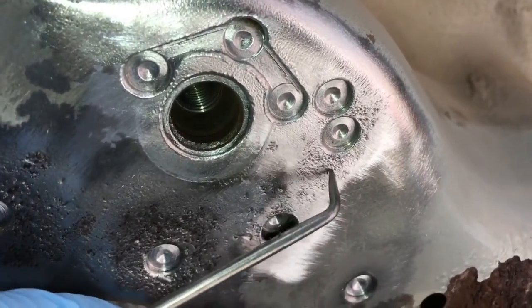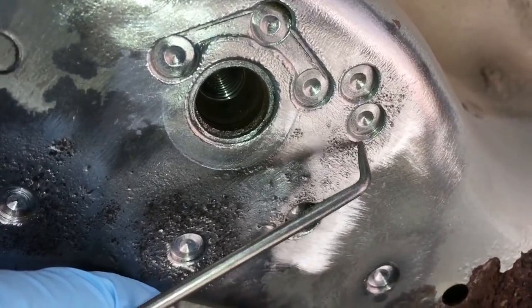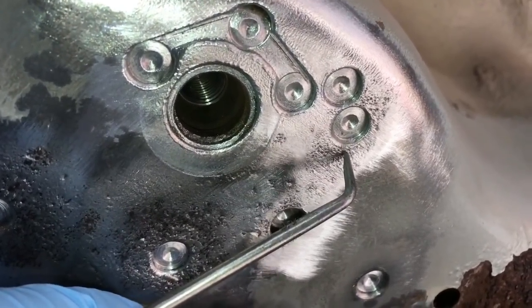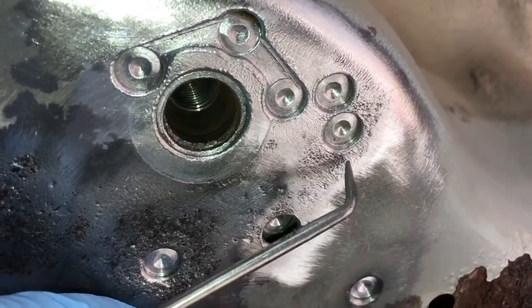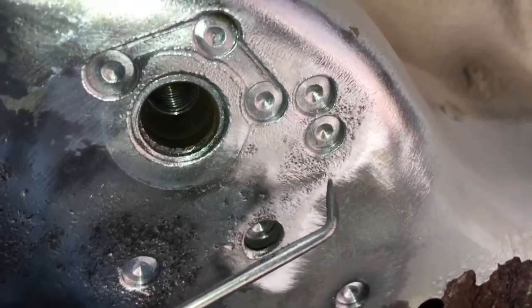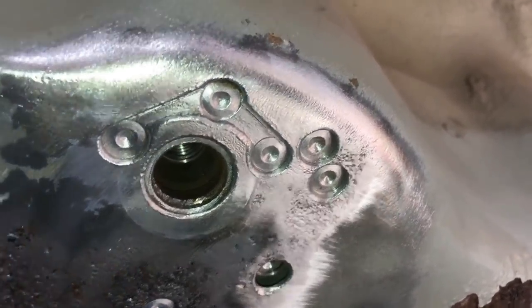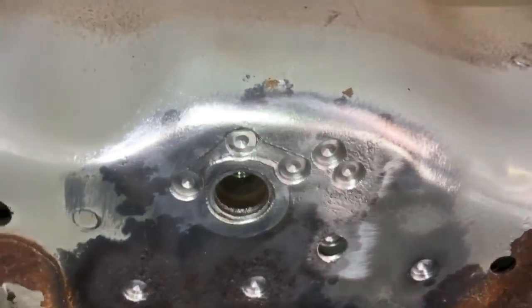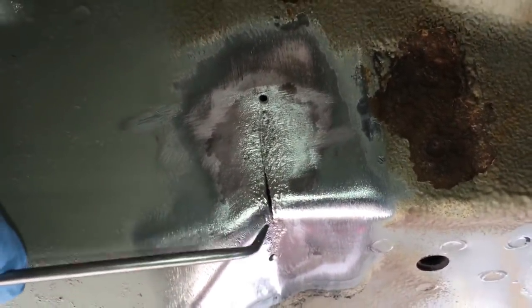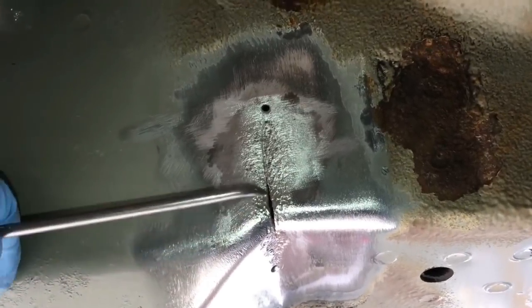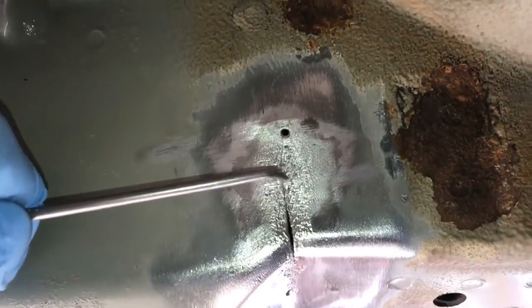There is a small crack that I've noticed here coming out of that area of spot weld going that way and stopping about here, so that also needs to be stop drilled or a section of metal removed before we go forward and put the weld through primer on there ready for penetrative weld. The other area, this crack has been corroded for so long that, as you saw in the video earlier, it actually opened up, and that metal is very thin, and that's as much corrosion as we dare take out without thinning or damaging the metal.